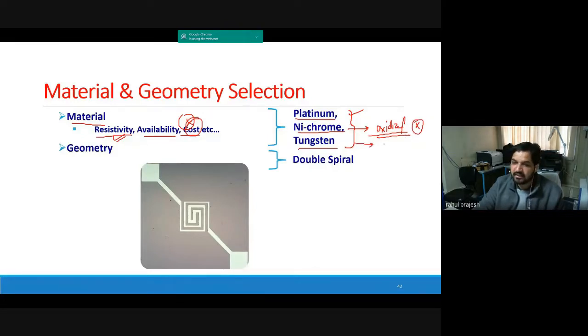Tungsten, on the other hand, also has tendency to oxidize, but less tendency. Okay. But for precise applications, most of the times you use platinum because it's a noble metal, and it doesn't get oxidized. So the material will be stable chemically and physically. It's very stable. So if it is stable, it will give you very constant resistance, and hence you will get constant temperature for a long period of time.